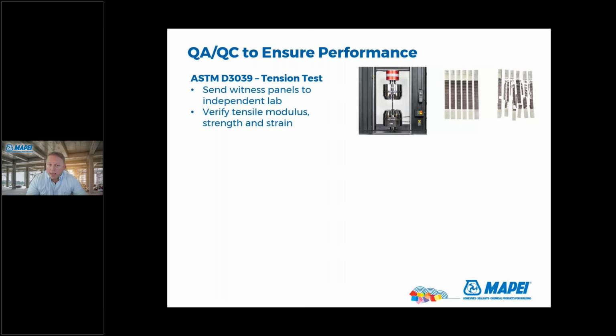We've seen this can be a common item. Manufacturers, we're not too crazy about it because it becomes more of a test of how well the contractor can make a sample for the lab. If the contractor doesn't squeeze all the resin out and you have real thick resin, well, it's going to lower your tensile strength value. Same if the contractor doesn't perfectly align the fibers in one direction and he has some waviness, that's also going to affect it. And so that can become a problem on some projects where the contractor made some bad samples, and you're looking at it going, how do we correct this?